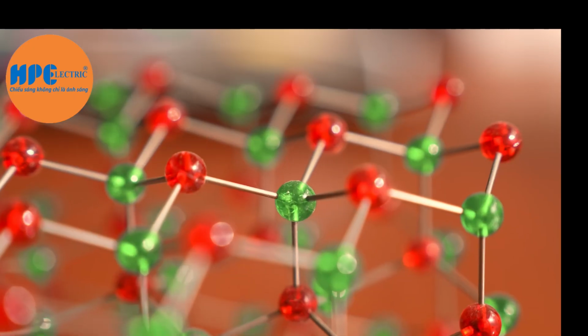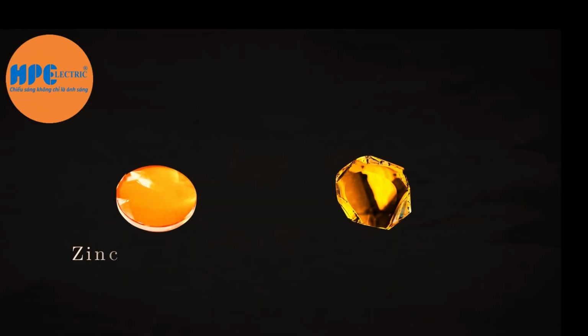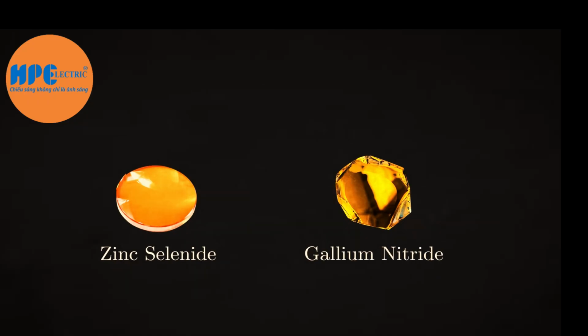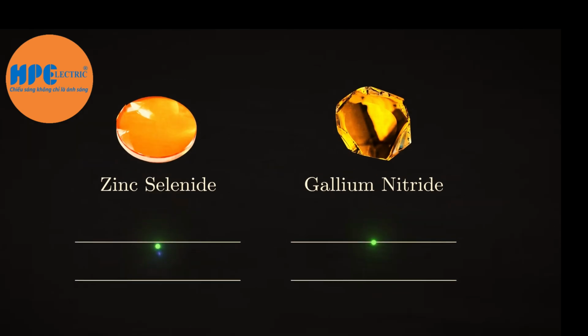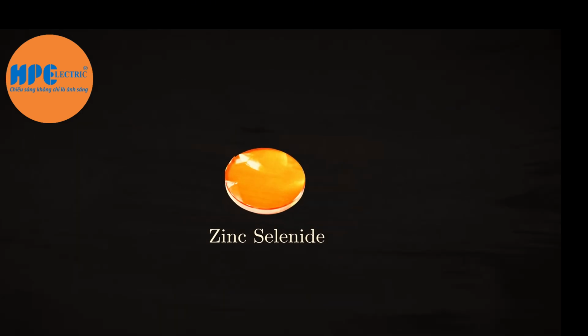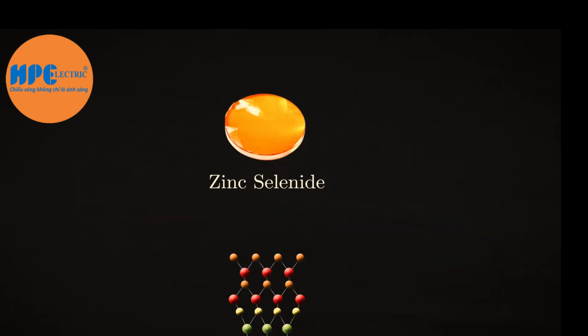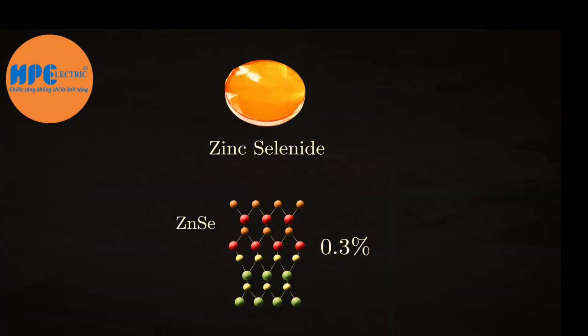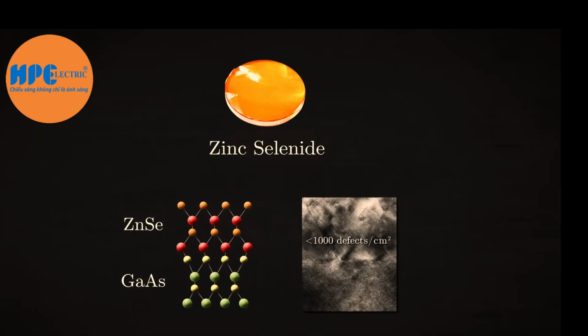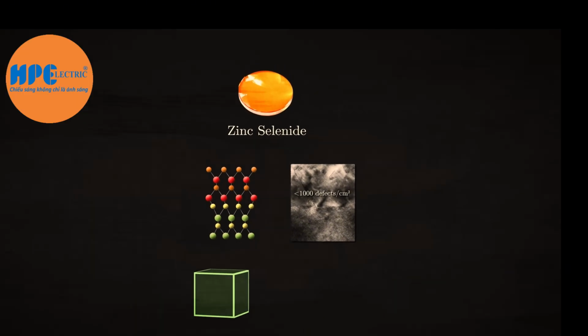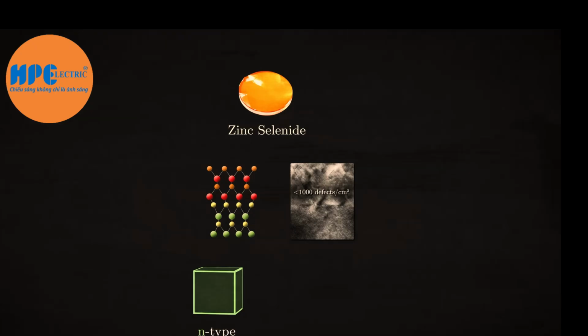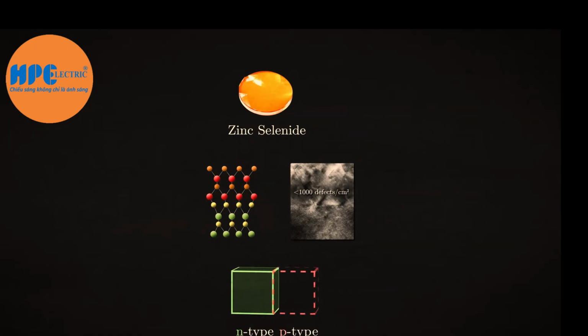But now the question was, with MOCVD under his belt, which material should he research? By this time, scientists had narrowed the options down to 2 main candidates, zinc selenide and gallium nitride. These were both semiconductors with band gaps theoretically in the blue light range. Zinc selenide was the far more promising option. When grown in an MOCVD reactor, it had only a 0.3% lattice mismatch with its substrate, gallium arsenide. Therefore, zinc selenide crystal had about 1,000 defects per square centimeter, within the upper limit for LED functioning. Its only issue was that while scientists had figured out multiple different ways to create N-type zinc selenide, no one knew how to create P-type.